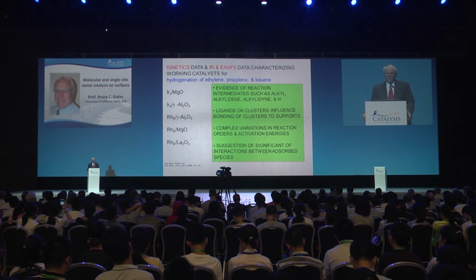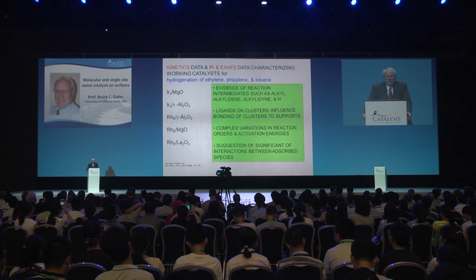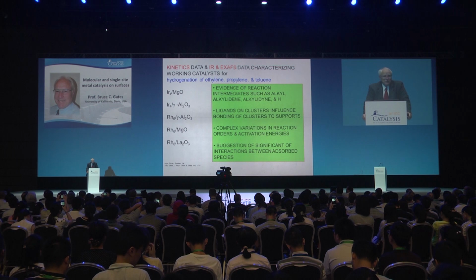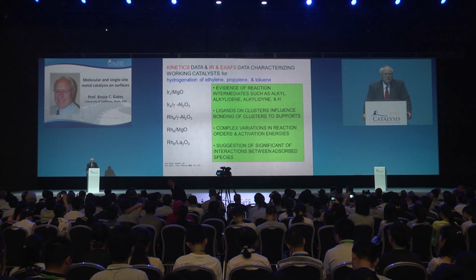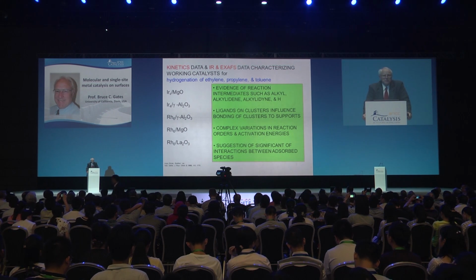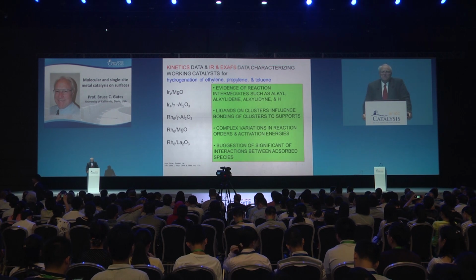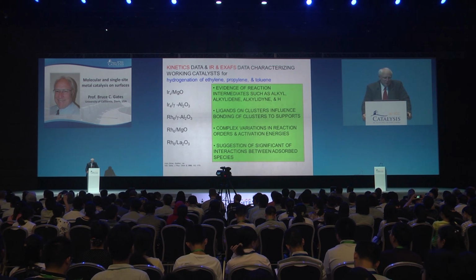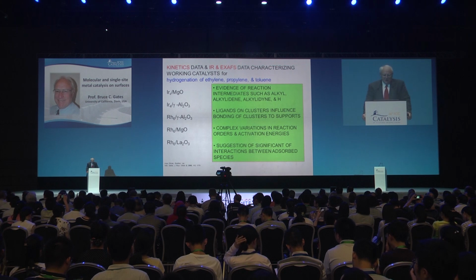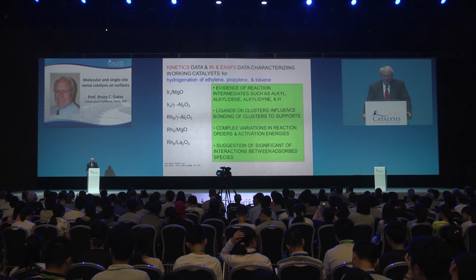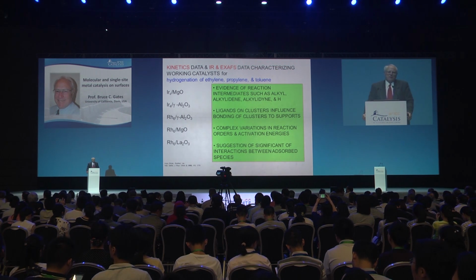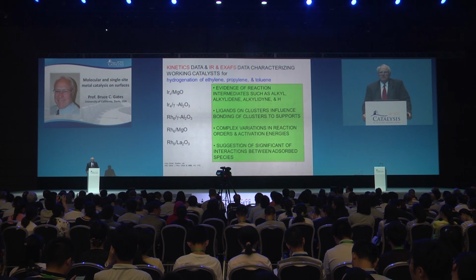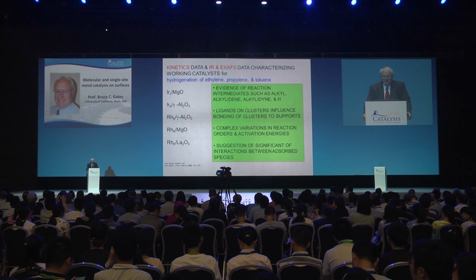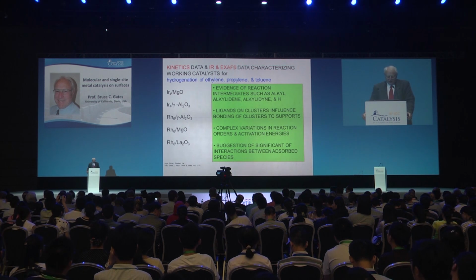The long and short of that is that once we get to clusters of this size, 4 and 6 atom clusters, there's subtle complexities showing up in the catalysis that are reflected in the kinetics. One hypothesis is that interactions between the adsorbed species are important, and the limit to what such species one can form, determined by the size of the cluster, is important in this whole story. There's much more to learn about all of this.